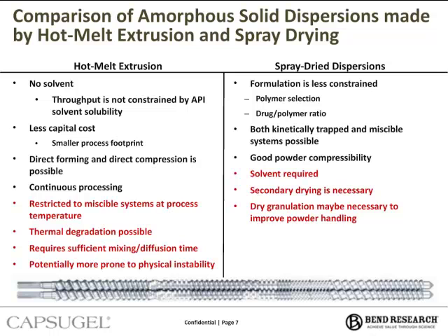So in general, hot melt extrusion is a continuous process that has a lower capital and manufacturing cost. However, the formulation is limited to miscible systems at the process temperature, whereas with spray drying the formulation is less constrained.